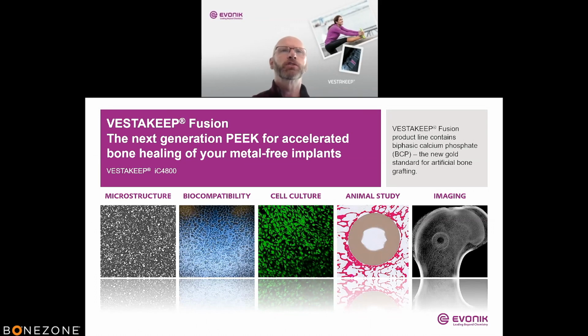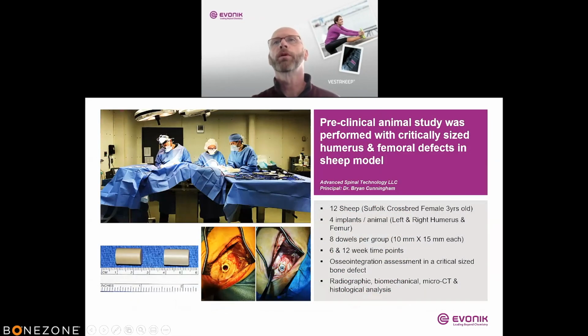What you're seeing here is just some of the work: microstructure, biocompatibility, in vitro work, histology, medical imaging. Really, a lot of work goes into developing a product like this. One of the major milestones of the project was to design a study to evaluate the osteoconductivity and the osteointegration of the PEEK composite, incorporating the biphasic calcium phosphate additive, and compare it to virgin PEEK in a sheep model. BCP, biphasic calcium phosphate, was the additive that we did choose after a lot of screening and thought and consultation.